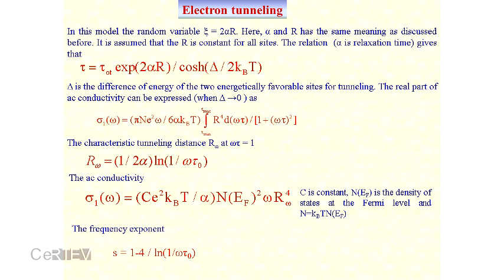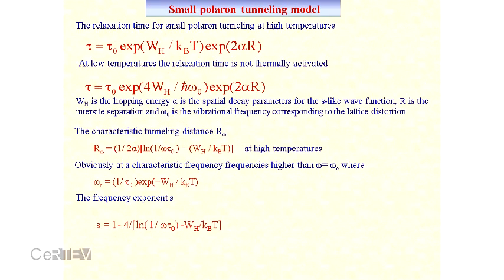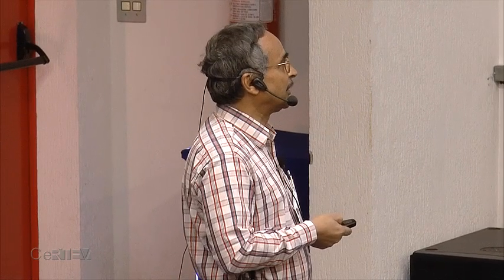I am telling you the consequence of the conductivity and the frequency exponent, because we will get information on the particular materials with the help of this theory. And for this small polaron tunneling, the relaxation time is assumed like this, and the consequence of which is that the frequency exponent can be expressed in this way. So in this small polaron tunneling model, you can see the frequency exponent is dependent on temperature, and as the temperature is lowered, the frequency exponent gradually decreases from 1 to some fixed value, or 1 to some, there is no limit of decreasing.